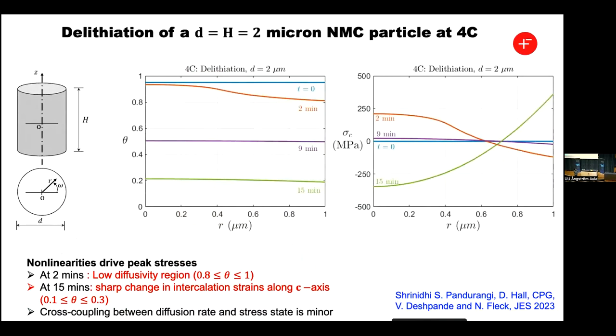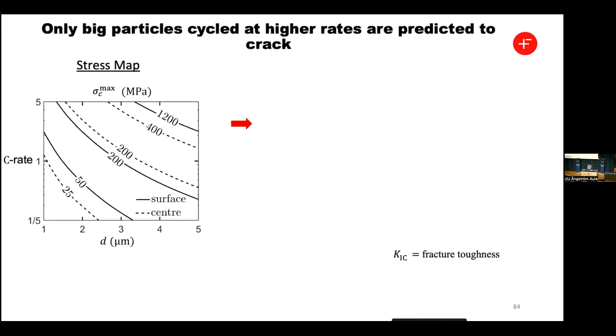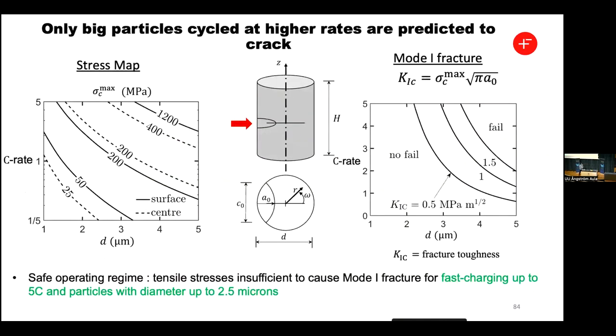As you pull something out, you can see the concentration changes across the particle, and it flips at the point where the diffusion coefficient has started to get very large. But the biggest question is, is this enough to cause cracking? So what he looked at was he created a little crack here, a little indentation as shown here. Then he explored a mode one fracture, the crack going in this direction: did you generate enough stress? And the answer is no. Unless you cycle fast enough or you have very large particles, your single crystal NMCs should not crack.